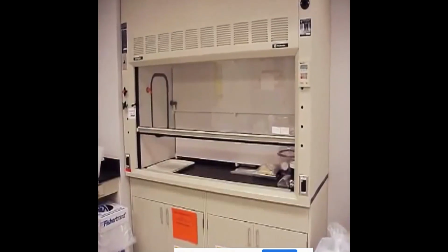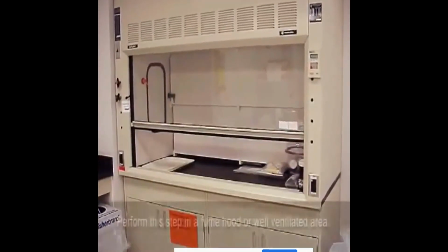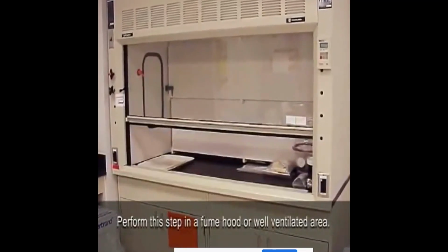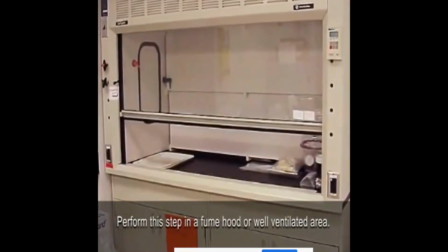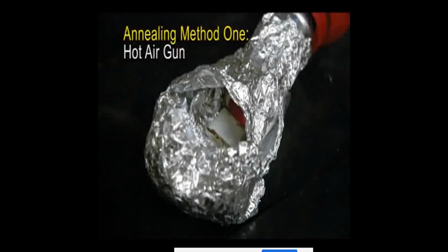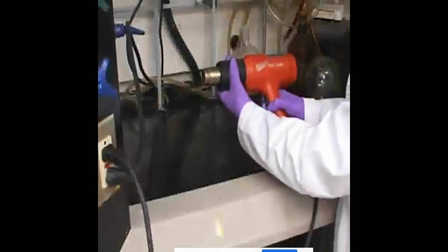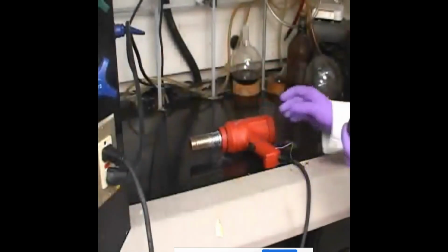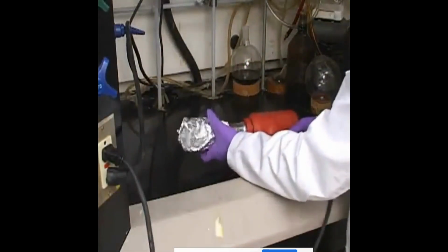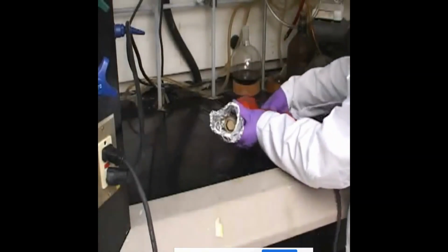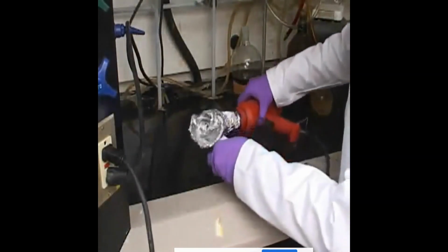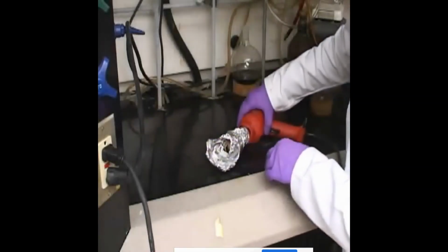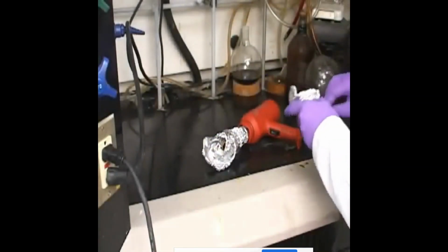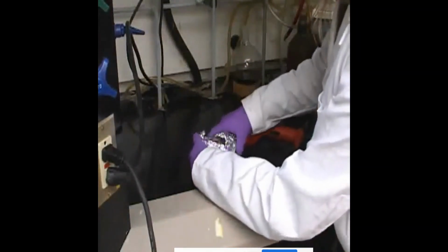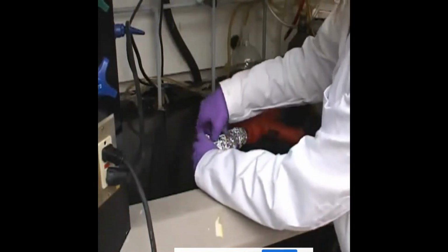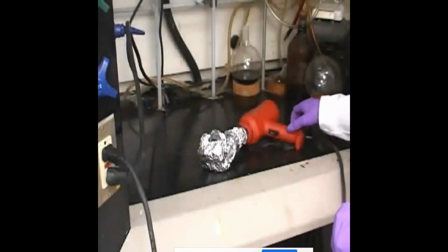Step 1. Anneal the titanium dioxide film on the glass slide in a fume hood or well-ventilated area. Use one of the following methods. 1. Make a simple tube furnace from a hot air gun. Start by removing the outer plastic casing at the base of the nozzle to prevent it from melting, then wrap aluminum foil around the nozzle to form an enclosed oven. The slides will lie flat inside this oven for the annealing process. Be sure to leave a small opening in the foil so that you can watch the slides for color change as they anneal. Turn the hot air gun on high or to 450 degrees Celsius. Let heat for 30 minutes.